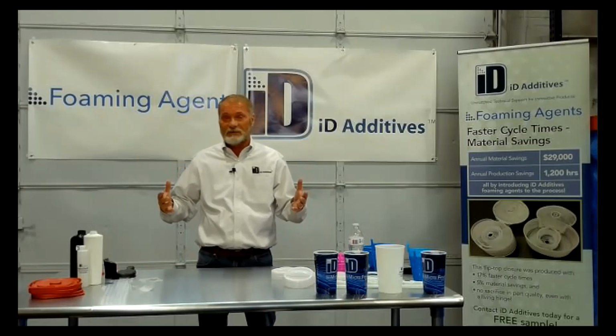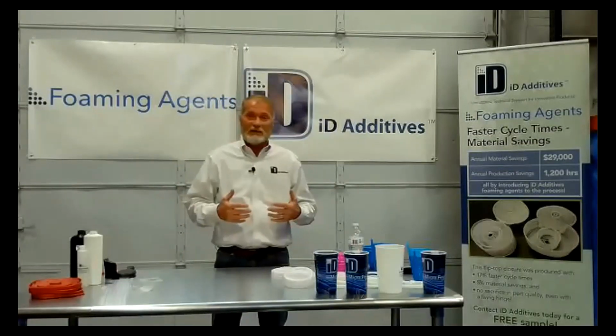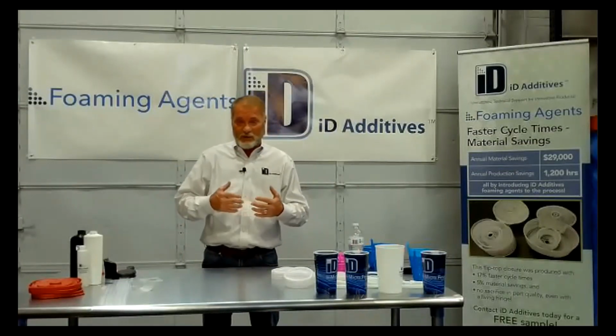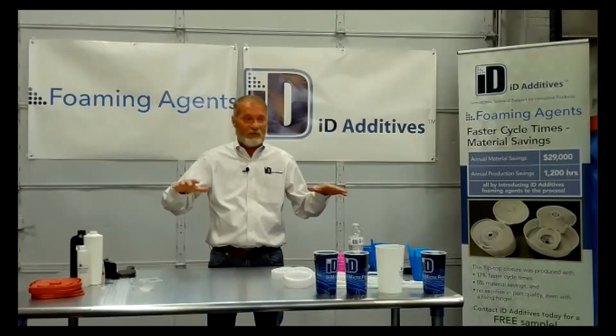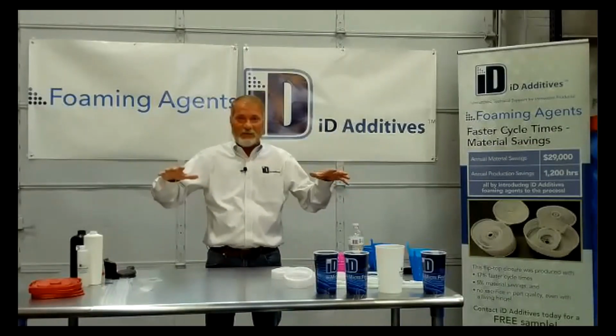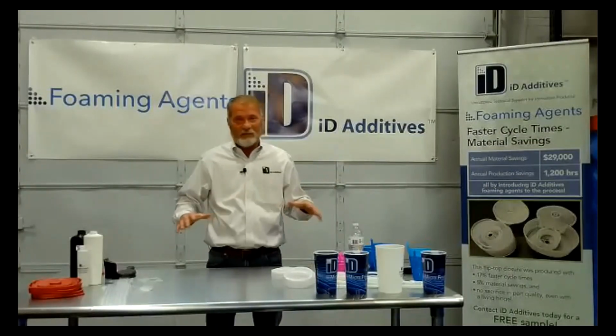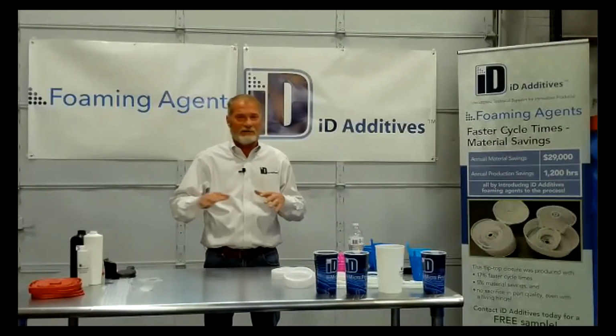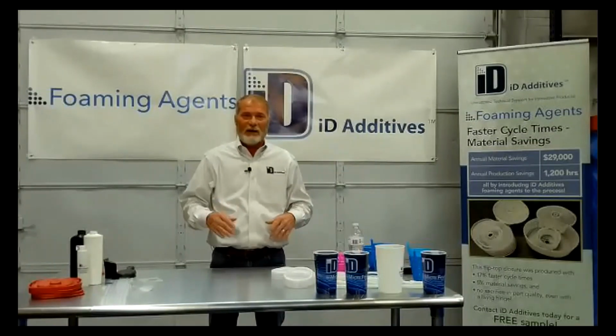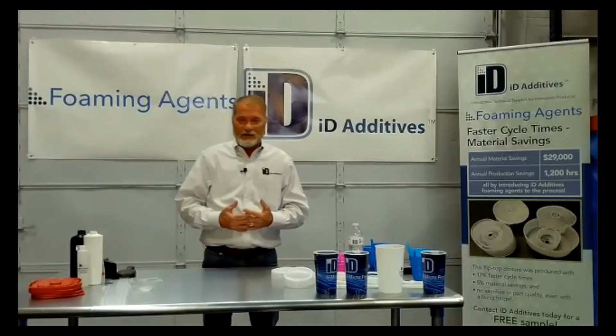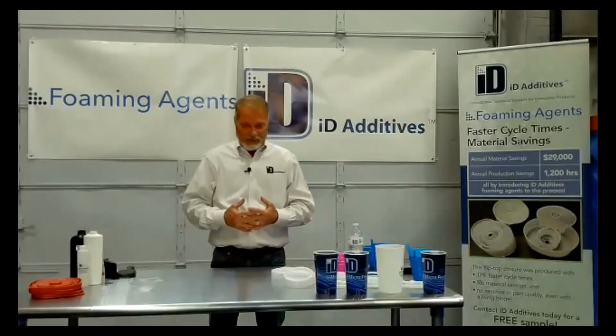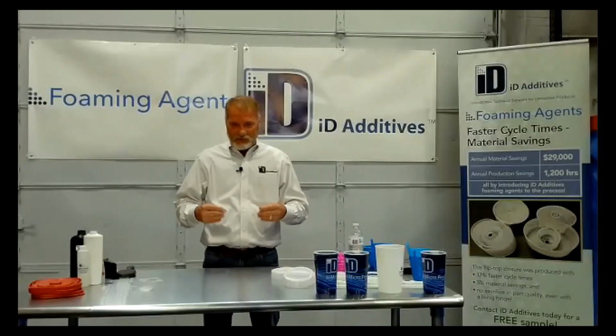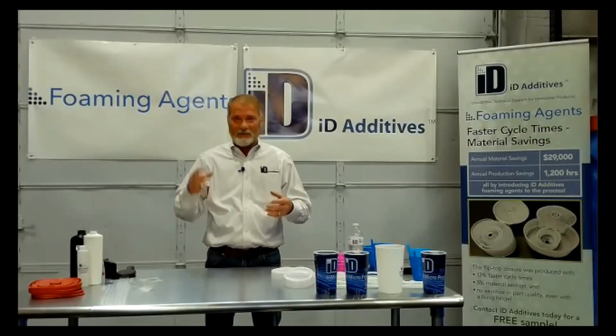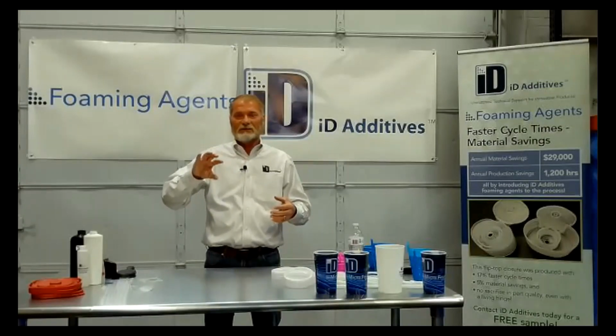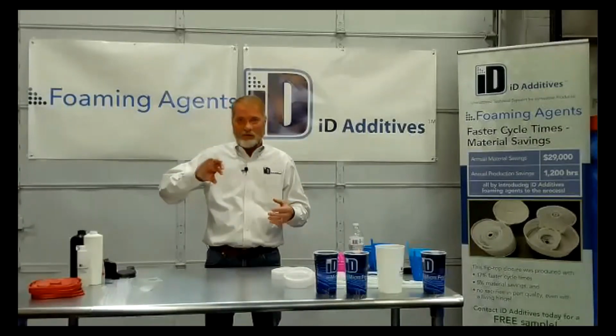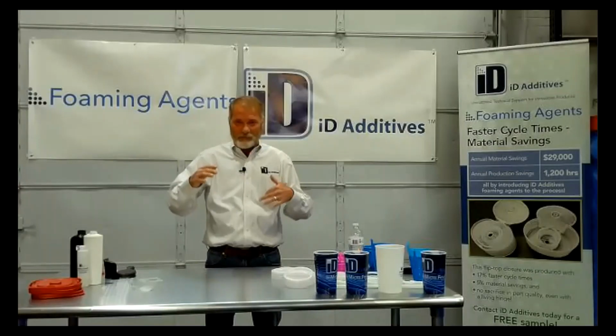With nitrogen. That nitrogen is a physical gas, so it will create voids in your part, and the voids, most of them are at infill, but you'll get voids everywhere in the part, and the voids will move around. It won't be consistent. By adding an endothermic, like our 5811 at 0.5%, that gives you the opportunity to bring down that nitrogen, so it takes some of that physical gas out, and it complements the endothermic.